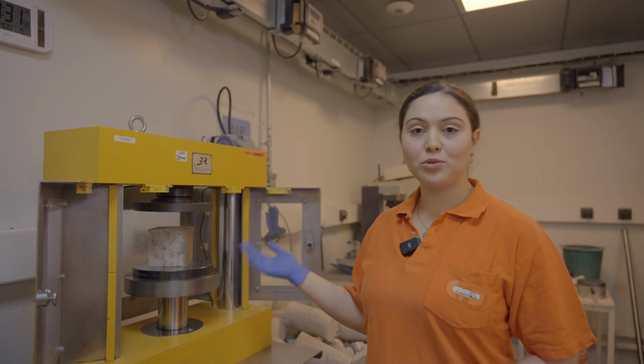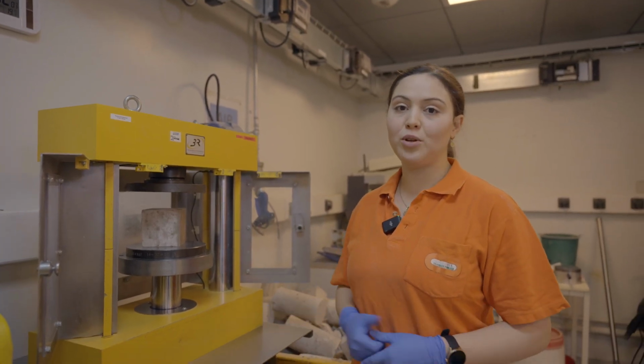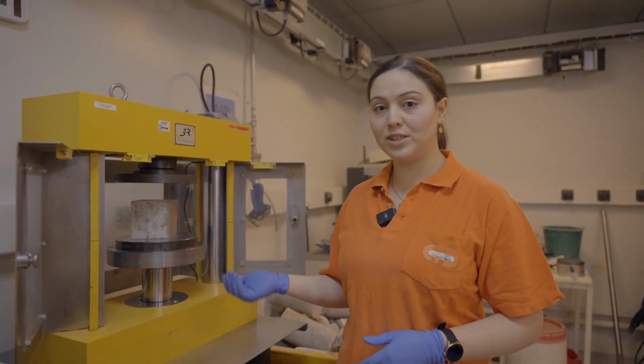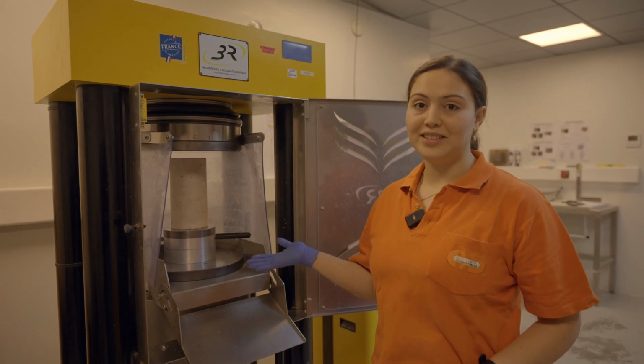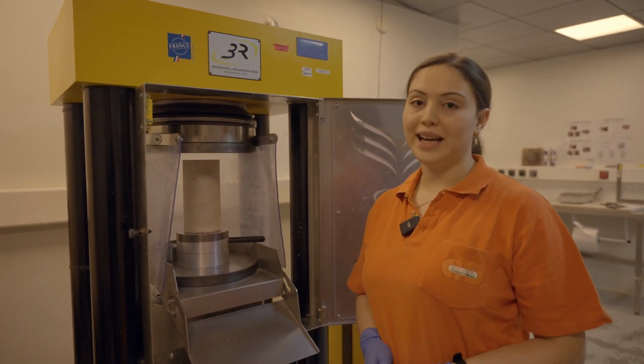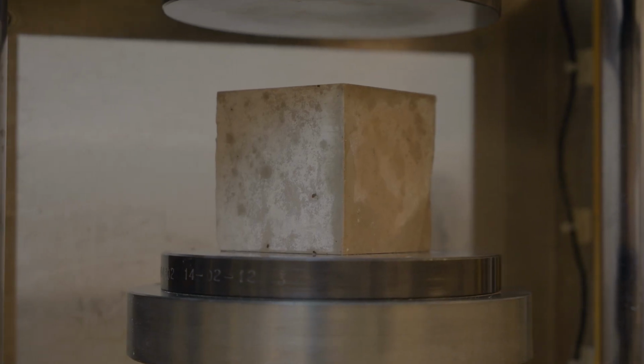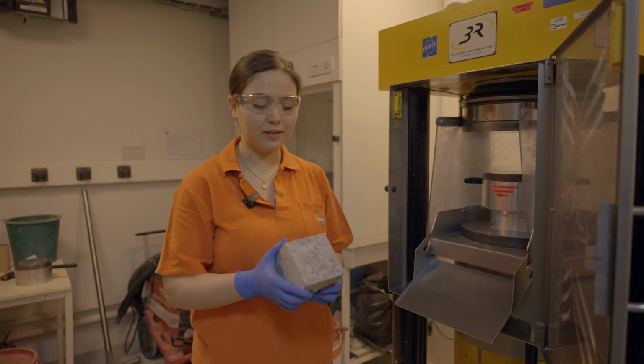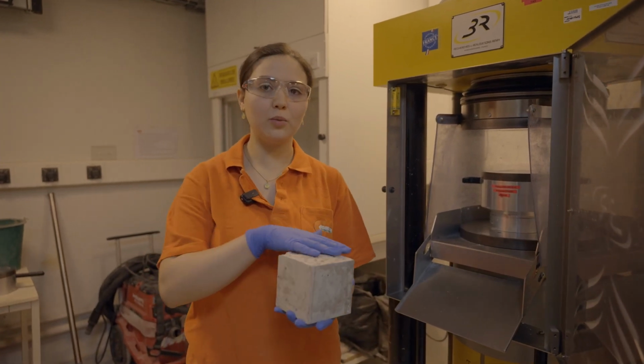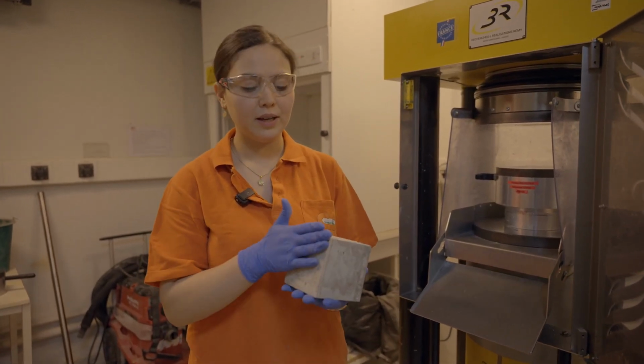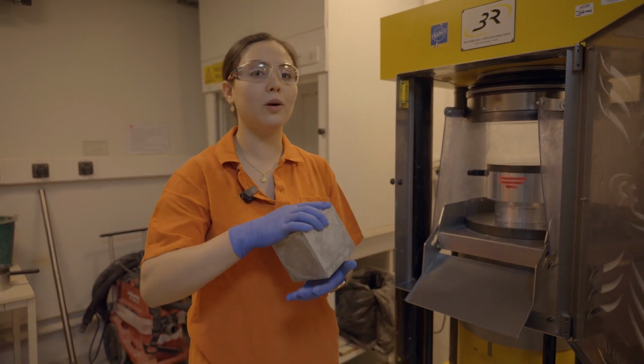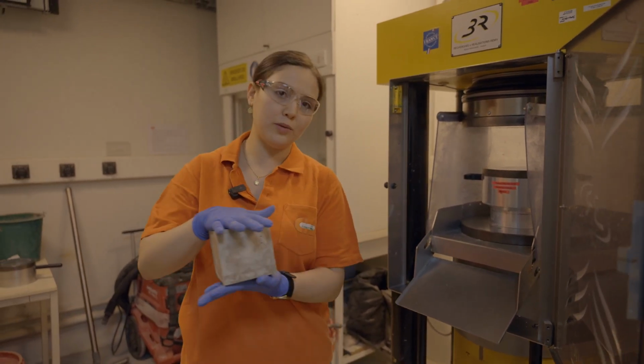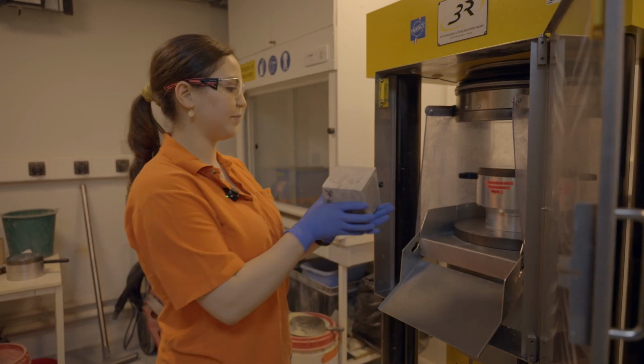This press is used for freeze-thaw test specimens and for low-strength mixes, but also for mortars and grouts. Whereas this press is used for specimens with high mechanical strength. For cubic specimens, there is no need for grinding since only one surface is exposed to air and all the others are smooth, so the load will be evenly distributed on both faces during compression.